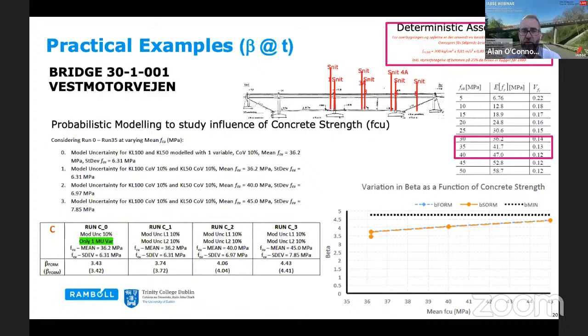And what we can see here is that where we worked from information from the original documentation around the structure, around the strength of the concrete, for example, we achieved a beta value which was below the target level. So we performed sensitivity analyses to see how that value varied as a function of alternative values for the characteristic strength, or the mean strength, I should say, of the concrete. And we can see in the table how the beta value varied as a function of the mean strength for the concrete as modeled statistically.